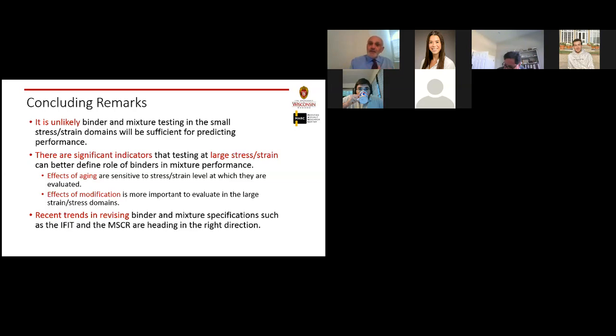Now, to correlate to the Hamburg has two problems. One of them is you're running in water. So you have two effects. You have a dry loading effect, but you also have a moisture damage effect. So we recommend that you analyze the rutting to separate the dry from the wet. If you take the dry, you find a steady state creep rate, which I believe is a much, much better indicator than the single point number of cycles or meters at 20,000 cycles and so on.